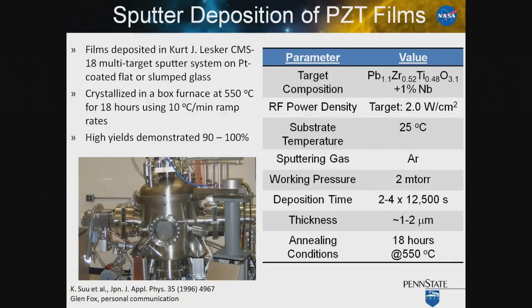And so in order for this technology to be feasible, we need some way of preparing on these thin, slumped glass optics a corrector element. And the approach that we've taken to do this is to utilize lead zirconate titanate thin films. We deposit these by a sputtering process, as shown here. We choose the composition of the piezoelectric to maximize the piezoelectric response and dope it to achieve high lifetimes under electric field. We had to work relatively hard to drop the crystallization temperatures for these piezoelectric layers so that we didn't deform the glass on which it was deposited.